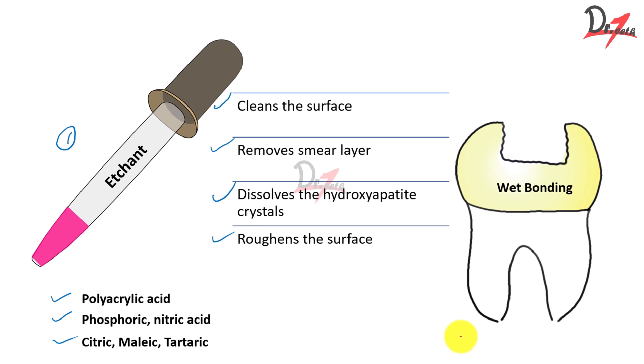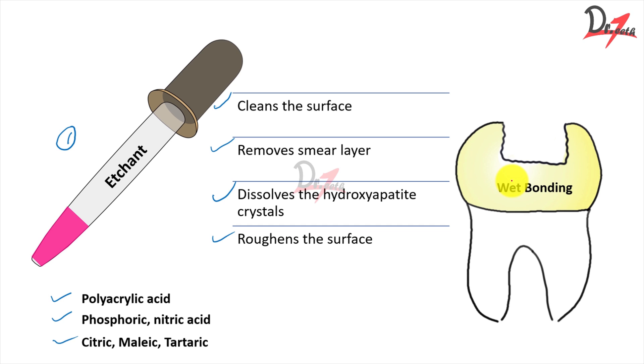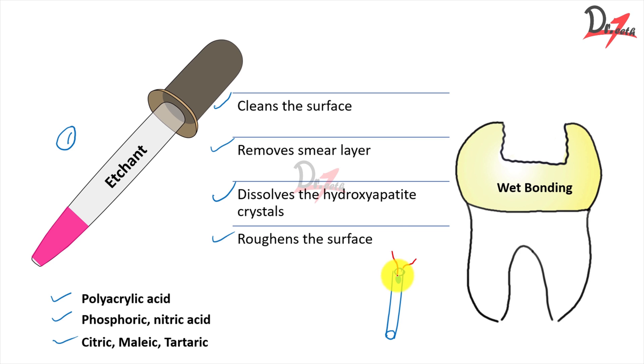Here I would like to talk about wet bonding. When we apply etching to the surface of the dentine, we allow it to stay for 15 to 20 seconds, then wash it off with copious water, then dry the surface very lightly by blowing air. We must not over-dry the tooth surface — we want some moisture to remain in the dentine; that is referred to as wet bonding. The water molecules guide the resin or restorative material to come inside and form tags within the dentinal tubules.